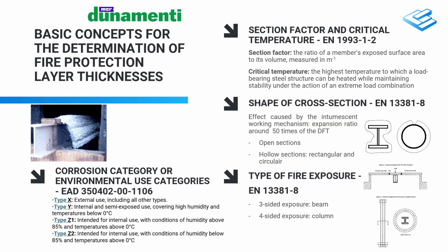However, with hollow sections, particularly the circular ones, this effect can cause a lot of problems. Since the paint particles originating from the original diameter of the circle must cover a larger diameter as a result of the foaming. Imagine that, and also you can look at that little drawing. So the foam can crack up during one phase of the foaming process. To ensure that the surface is filled in during reforming after the crack, a much thicker coating layer is required on circular cross-sections. It causes higher dry layer thicknesses for the circular hollow sections in any kind of solutions and any kind of products.